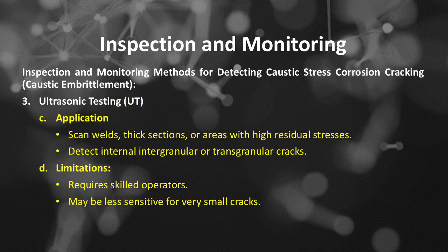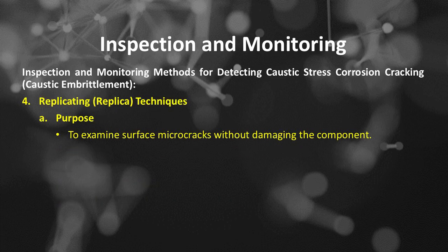Ultrasonic testing is applied to scan welds, thick sections, or areas with high residual stresses, and detect internal intergranular or transgranular cracks. The limitations of ultrasonic testing: it requires skilled operators, and may be less sensitive for very small cracks. Inspection and monitoring methods for detecting caustic embrittlement.